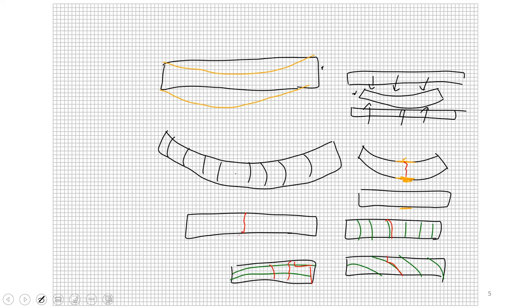So again, the actual path a crack will take, or in this case, the formal name we're talking about here is a split, is very difficult to predict. It's a combination of how the individual boards were cut in relation to the growth rings, the exact details of the thickness and the strength of the growth rings, all these things. The key thing to keep in mind for splits is that they are formed by stresses from the milling process, and they almost in all cases will go from one surface of a board to another surface, though the actual path can vary significantly depending on the properties of the wood.